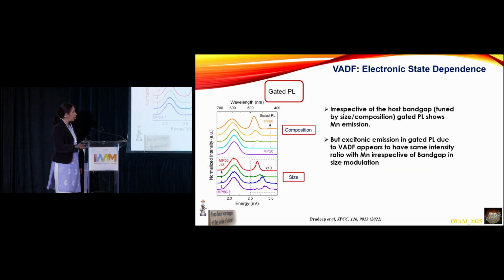So when I look at the effect on the VADF as a function of composition, I see that the host band gap is coming up at a particular energy onwards. So basically, if the band gap is decreasing, I am seeing an increase in the delayed fluorescence. But unlike that, if I were looking at the variation in size, irrespective of what the band gap is, I see the same amount of excitonic emission, almost no change. So this suggests to me that it is not the lowest energy state, but actually the higher energy states.